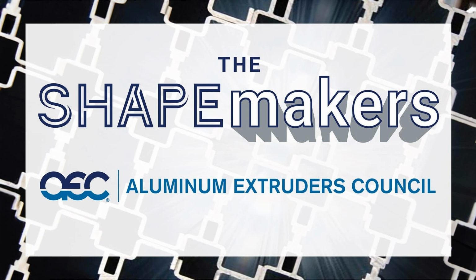That's impressive. Incredible. What about, I know a lot of extrusion is either painted or anodized. Can you recycle that post-consumer scrap as well? Well, anodized extrusions are treated just like any unfinished extrusion when it comes to recycling. That's because the anodized coating is generated from the base aluminum metal and has the same constituents as the aluminum. But the painted extrusions are a bit different due to the addition of the paint, which gives off VOCs when the extrusion is heated to the melting point. So you can still recycle painted extrusions, but the total quantity may be limited by the air treatment equipment and the emissions permits for your particular cast house.